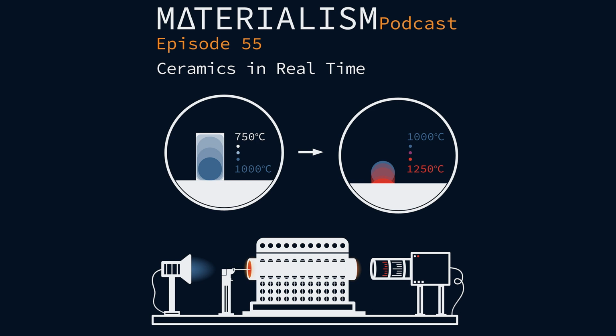One important point is that the temperature must rise very quickly, because that's the industrial condition, up to 80 degrees per minute. And this was incredible; we still find interesting things in that technique after so many years. It started in the beginning of the 2000s. By looking at a raw unfired sample, of course, you follow the pyroplasticity of the material. The viscosity lowers and the material starts flowing over its own weight, so it goes down. It goes down at different speeds depending on the composition, depending on how many glassy phases it developed inside, and so on. It's very complex.